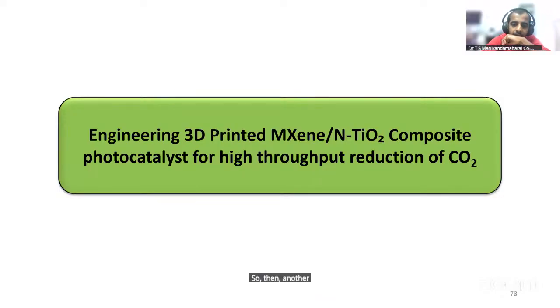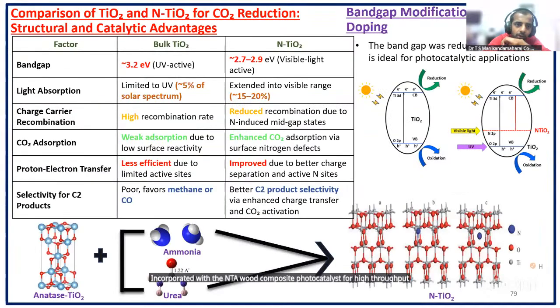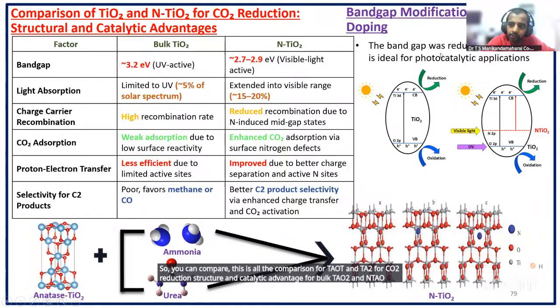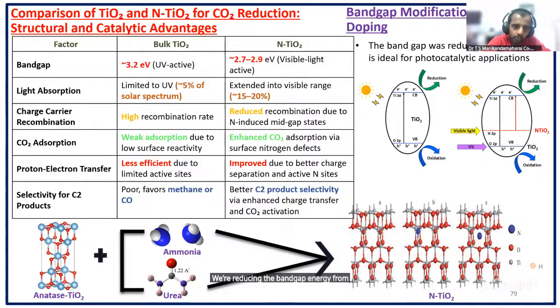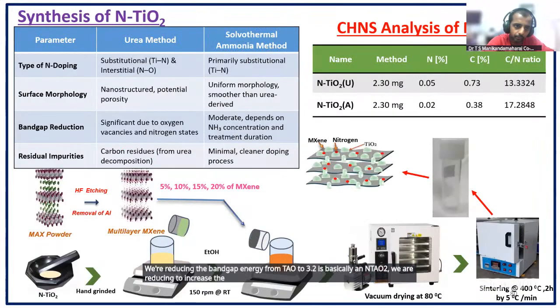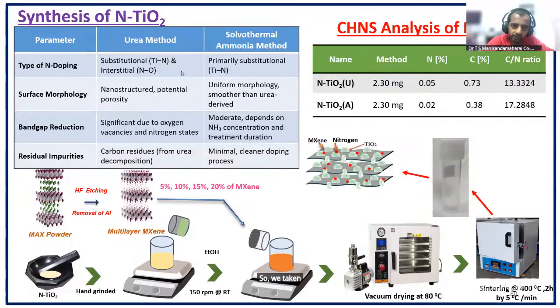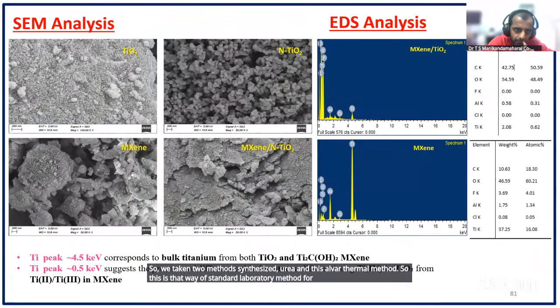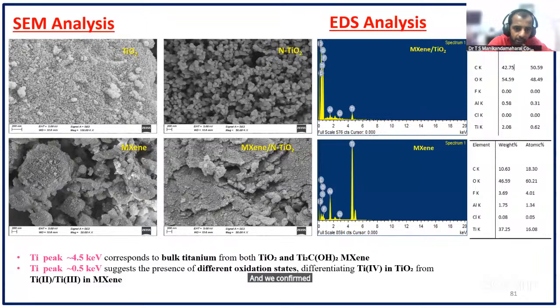Another application of engineering is MXene incorporated with the NTiO2 composite photocatalyst for high throughput reduction of CO2. You can compare TiO2 and NTiO2 for CO2 reduction, the structure and catalytic advantage for bulk TiO2 and NTiO2. We are reducing the band gap energy from TiO2's 3.2 eV to increase the performance. We took two synthesis methods, urea and solvothermal. This is the standard laboratory method for preparing, and we confirmed the synthesized MXene and MXene incorporated material by SEM.